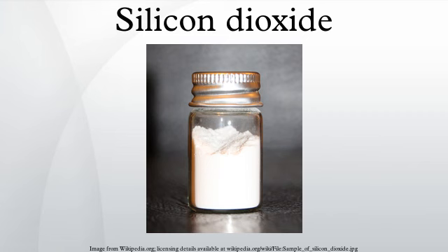From silicate esters, many routes to silicon dioxide start with silicate esters, the best known being tetraethyl orthosilicate, TEOS. Simply heating TEOS at 680 to 730 degrees Celsius gives the dioxide: Si(OC2H5)4 gives SiO2 plus 2O(C2H5)2. Similarly, TEOS combusts around 400 degrees Celsius: Si(OC2H5)4 plus 12O2 gives SiO2 plus 10H2O plus 8CO2.